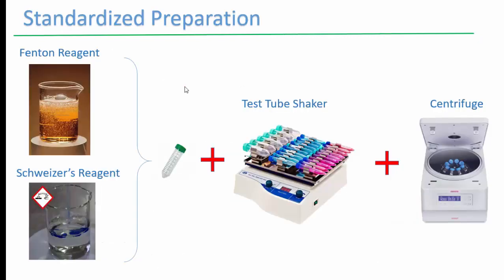So essentially, it's a two-step process for most samples. One, using the Fenton reagent to decontaminate the sample and clean it up, and then the second, using a Schweizer's reagent for removing cellulose. Now again, you only need the Schweizer's if you're dealing with influent samples that have a lot of cellulose material in there, a lot of toilet paper.